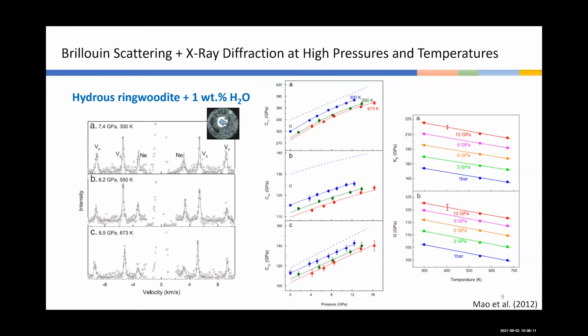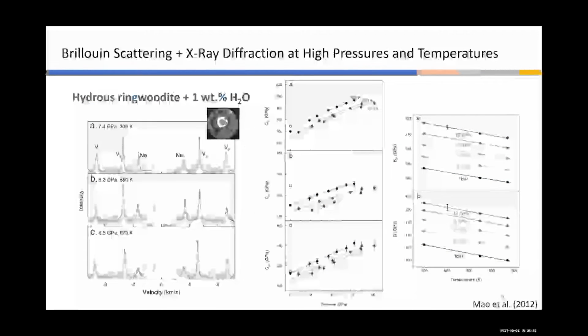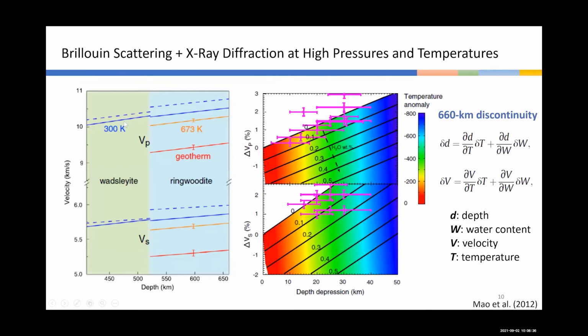Although at that time we could only reach 673 Kelvin, this temperature is really low. So this is our first simultaneous high PT experimental work. Anyway, using this facility, in this work we determined the combined effect of pressure and temperature on the single crystal elasticity of hydrous ringwoodite. From this work, you can see that we have the 300 K measurements, and then the maximum temperature velocity measurements at 673 Kelvin. And of course, we have to extrapolate our experimental results if we want to model the sound velocity of hydrous ringwoodite at mantle conditions, so we extrapolated it to the mantle geotherm.